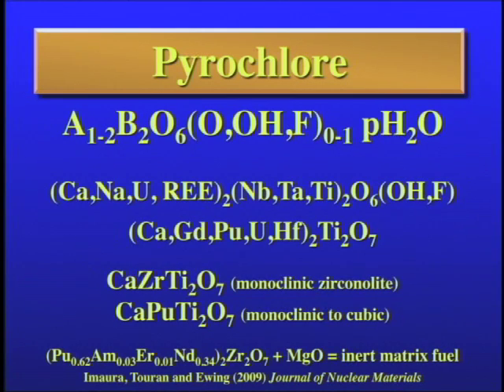The pyrochlore, this is the general formula. If you just add up the cations, you see you have 4 and the anion 7. This is just a simple fluorite structure, AX2, except you're missing an anion and you have 2 cations. Okay? But it's just AX2 except it's AB, and it's not 2, it's 7, and you've taken 1/8 of the anions out. The pyrochlores occur naturally with end-member compositions on the B side of niobium, tantalum, and titanium. The titanium will be important.